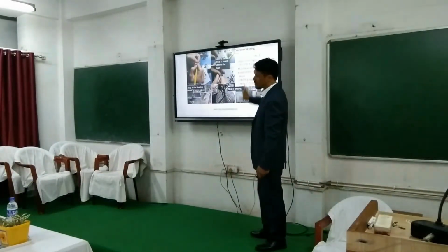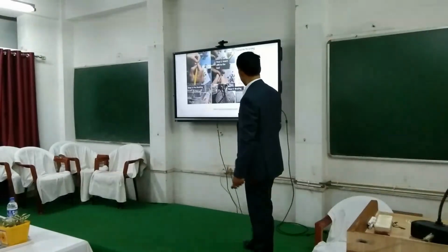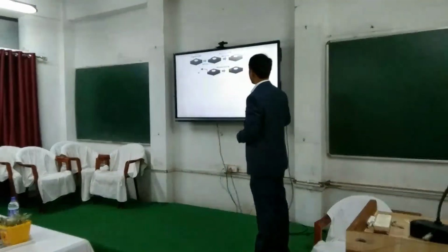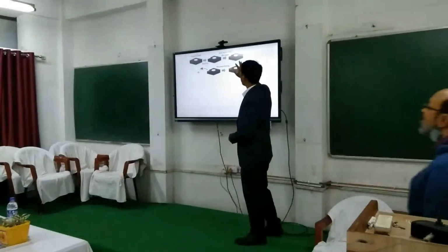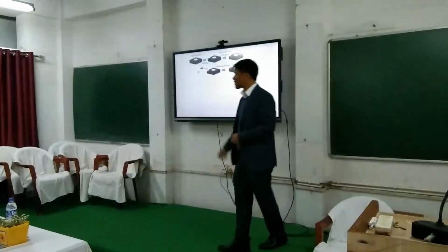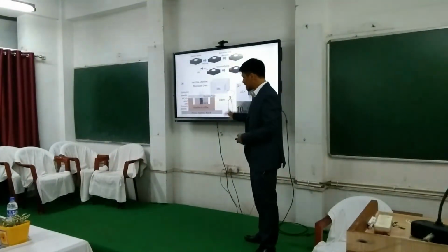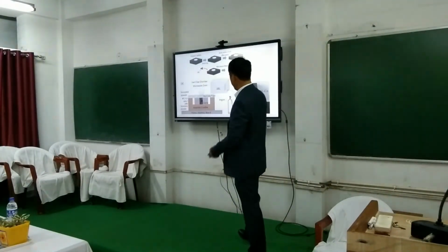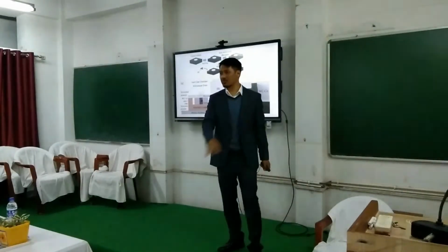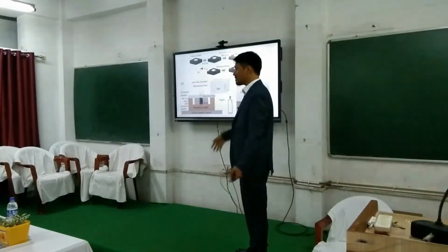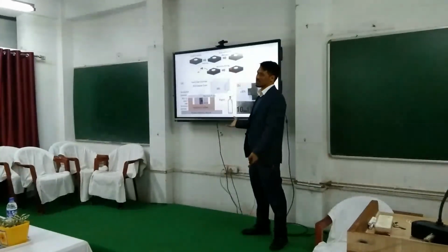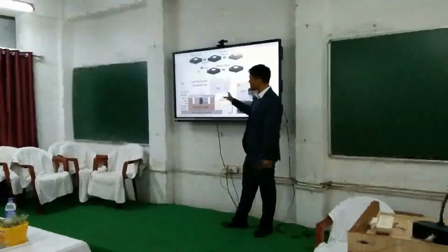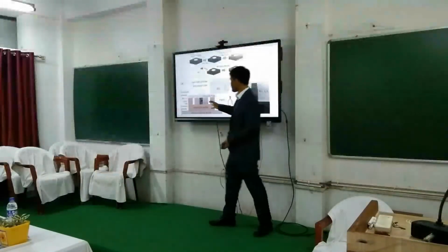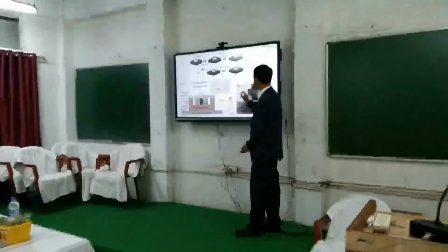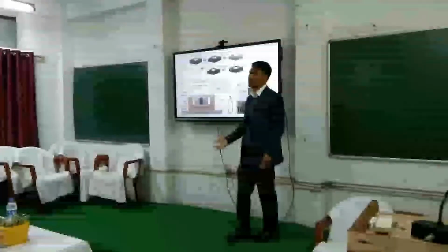The brazing, which is conventionally done by vacuum brazing, takes around 2 to 3 hours for the entire process. But we have done this in microwave. We have taken tungsten carbide and used braze alloys in order to get the microwave brazing. These are some results which we have got. Similar to earlier, we have a microwave oven, and these microwaves, by the way, are the normal ones, which cost almost 3 to 4,000. The only thing is we have made a chamber and put in some argon gas so that the active braze alloy does not oxidize. We have clamped the tungsten carbide with the cubic boron nitride, applied some braze alloy and undergone microwave heating to form these joints.